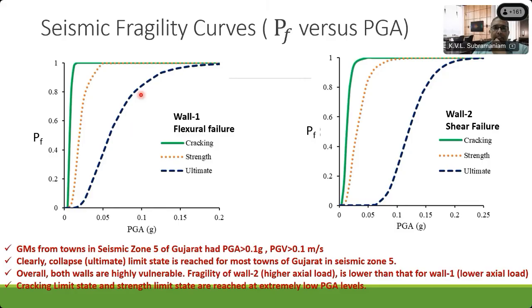So if you look at 0.1 G, it would indicate that almost 80% of the walls, which are basically flexure walls, would have failed. Similarly, if you come here at 0.1 G, about 30 to 40% of the walls which were designed to fail in shear would also fail. So our analysis is predicting that we would expect to see very high failures in walls which are subjected to in-plane shear loading under an applied compression.